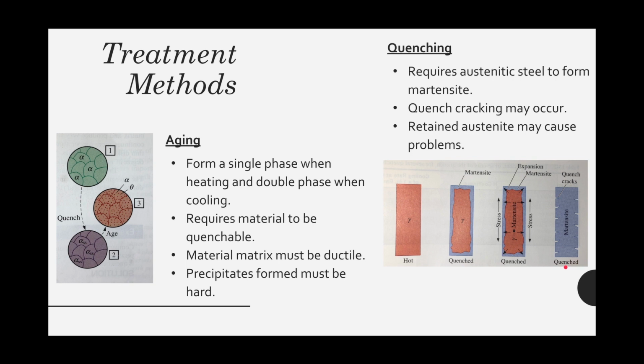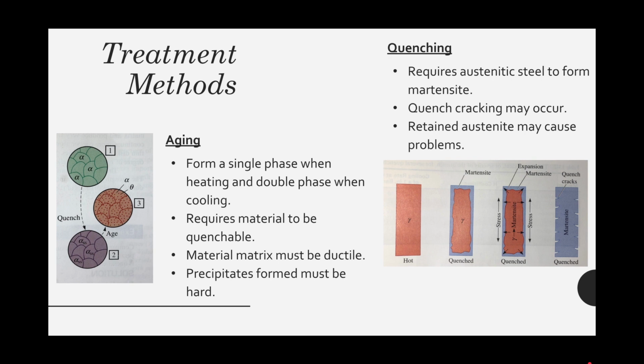For stainless steel austenitic Nitronic 60 annealed, retained austenite is not a problem since it mostly happens in higher carbon steels. This type only has 0.1% carbon. Quench cracks can also be avoided by heating the steel to a specific temperature so that when quenching occurs, the residual stress does not exceed the tensile strength.